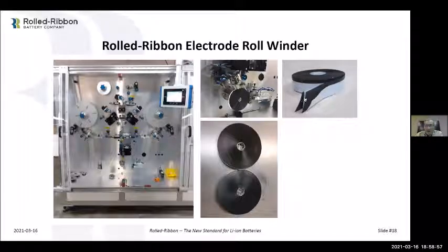When you look at it when it's done, it makes sure that this edge sticks out a little bit this way, and that edge sticks out a little bit that way, so that it comes in contact with the two opposing bands. When you get done winding an electrode roll, you see this. So this is two rolls, looking at one side and the other. The anode is coated on copper, so you can see the color of the copper here. You can see the edge of the copper shows on one side, and the other side sticks out the other way. This is another one flipped upside down.